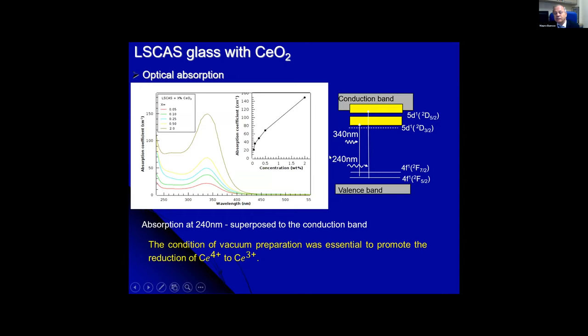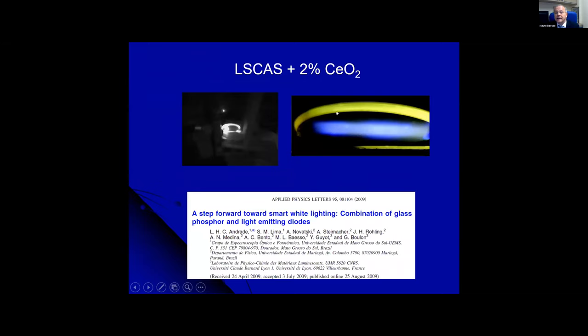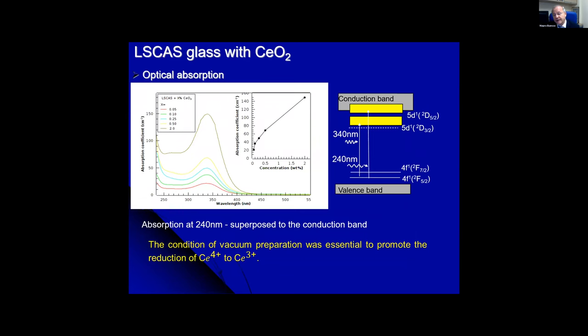You can see there are two main absorption bands here. In the UV, these are overlapped with the conduction bands. And then we were trying to study that and doing the measurements. What we observed was this yellow emission, and you can see the sample is excited with blue light. You can see the yellow emission. It's not easy to get yellow emission or red emission from glass. People from this area know that very well. In fact, red emission is quite complicated.